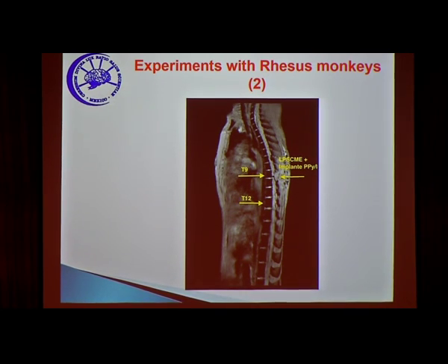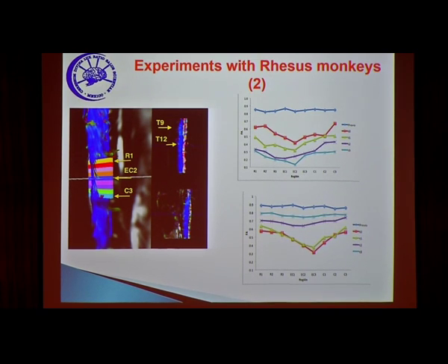And we also have started experiments with monkeys as a previous step to go to human beings. And this is an experiment with rhesus monkeys. They receive a transection lesion, and then the injection of particles. This was a thin film implant, and what we observed was that in the case of the control monkey, he received no implant, and the fractional anisotropy is going down, meaning that the water can move in every direction without a preference.